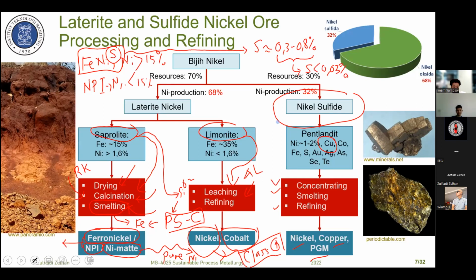If you see the ferronickel plants worldwide, there is always nickel refining there, always desulfurization facilities there in order to remove sulfur. For nickel pig iron, the nickel content is less than 15%. The common content is around 10 to 12%. In that case, the sulfur content is around 0.2 to 0.5%, and they sell the product with the high sulfur content. This is what we call nickel pig iron. Nickel pig iron is not refined, and also the nickel content is less compared to ferronickel.